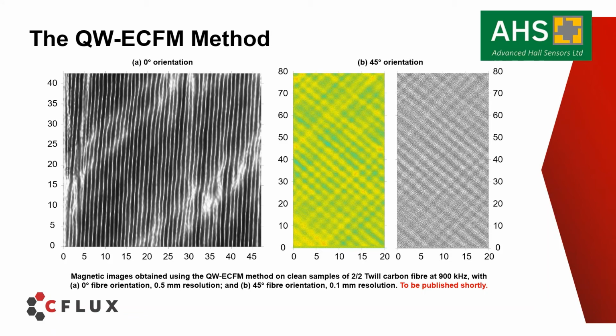The right-hand image shows a magnetic image obtained from the same clean sample where no defects were induced. Instead, the sample was rotated by 45 degrees so that the fibres were not aligned in the vertical direction, preventing the linear eddy current region from forming properly.